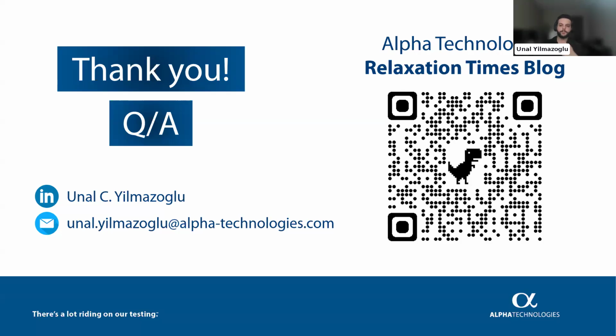Again, great question. For the processability, especially for mixing, which I haven't shown in this case study webinar, you could run a strain sweep test. By not just looking at the G prime versus strain data, but also looking at the S prime versus strain data, if you see some inconsistencies like sharp peaks and abrupt changes in the data, it gives you an understanding of whether this material is feasible to process or you should make some modifications. On top of that, with the end functionalization, you could also identify these differences with LAOS testing.